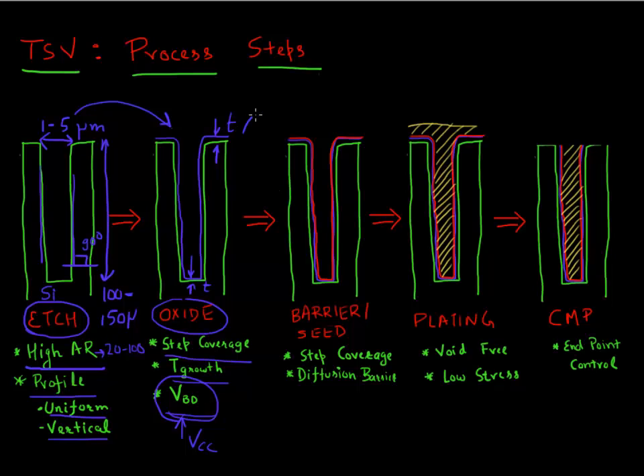The next process, which is after you fill it up with oxide and before you fill it up with a metal, is you want to put a barrier layer or a seed layer of metals. So this barrier layer will prevent the diffusion of the metal into your silicon, or diffusion of your metal into your oxide. Another thing important is the step coverage. So you want the same thickness of this metal on the top and you want the same thickness on the side. And this metal that you're filling in is a good diffusion barrier.